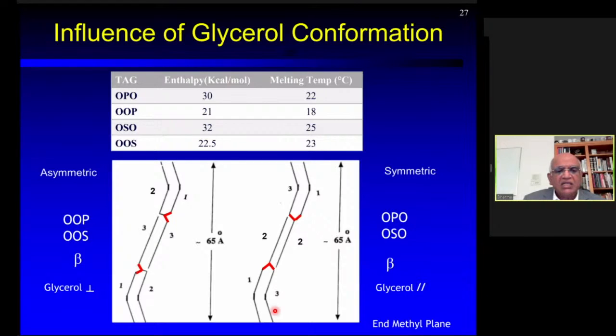As these triacylglycerols pack together, they form a trilayer structure, with the saturated chains segregating and forming a middle layer, with the oleoyl chains packed on the top and bottom, as is shown here. Similarly, here as well, the saturated chains are in the middle and the oleoyl chains are on the top and the bottom. However, here the saturated chains are attached at the 3 position. That makes the glycerol orientation perpendicular to the methyl-end plane. But here in this pair of compounds, they are parallel to the methyl-end plane.